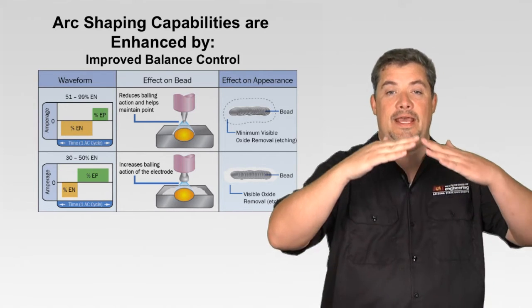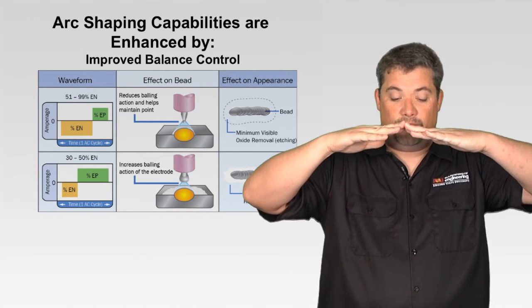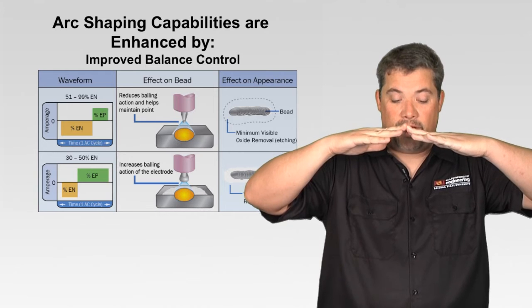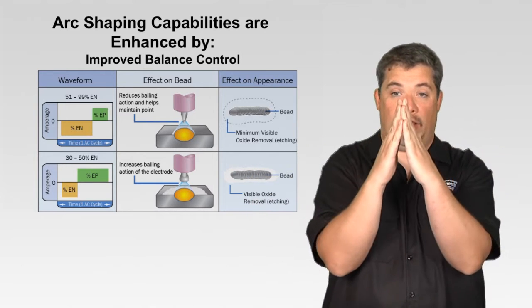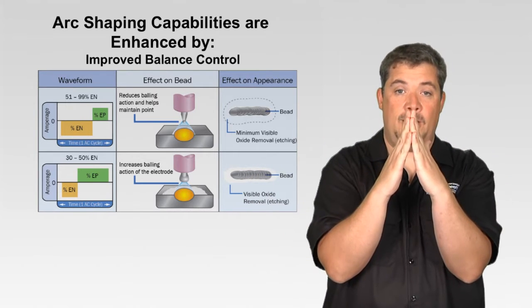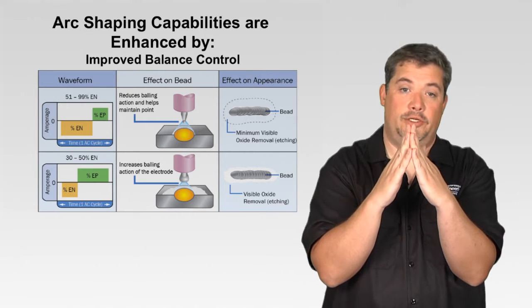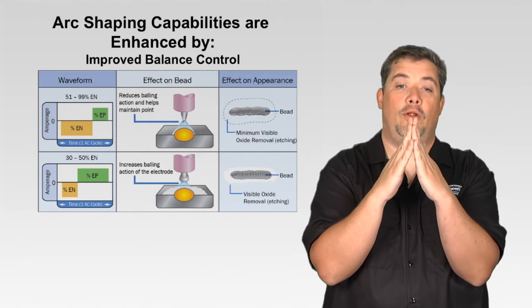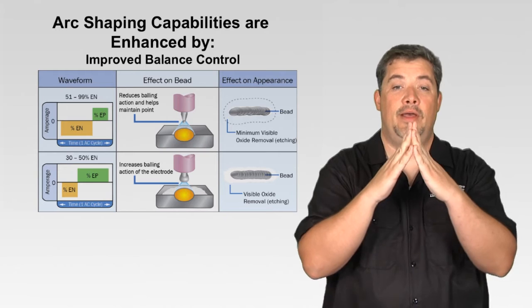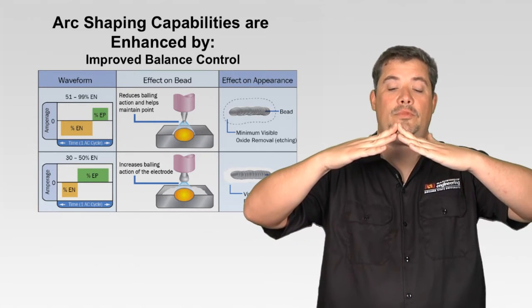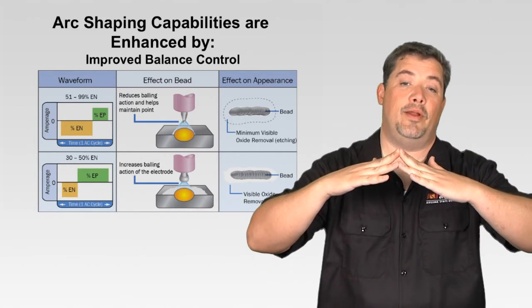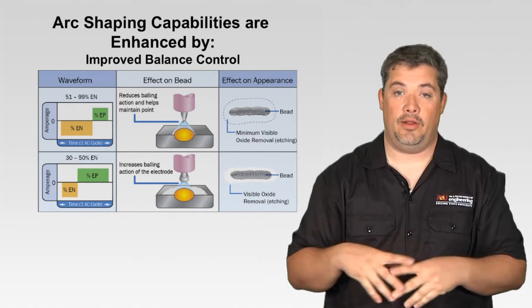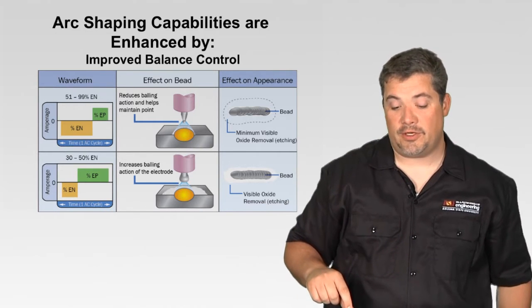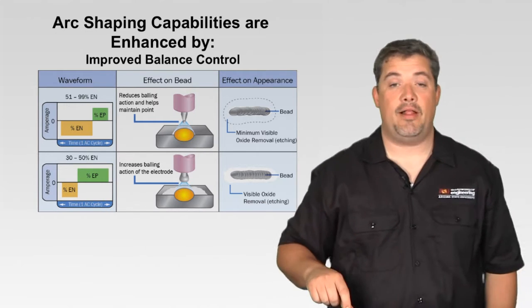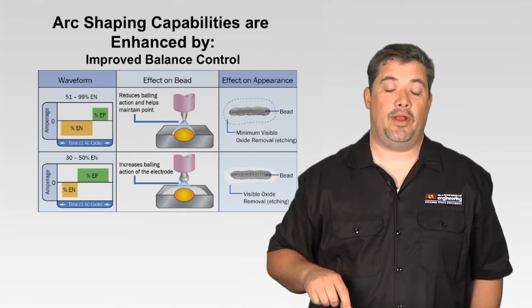So when I increase my percent electrode negative, I get a narrower bead and I get a little more energy going into the part. When I use more electrode positive in time, just like before, I might have a little bit wider bead, but I'm getting a whole lot more etching going on. So I can really start to shape that bead by changing the balance control more so than I was with